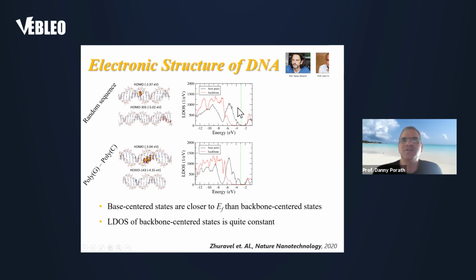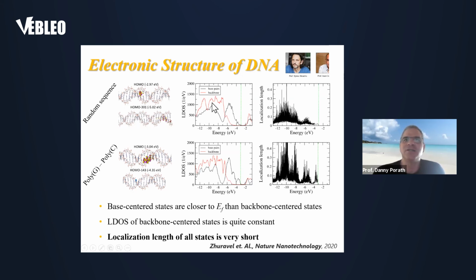So you can see that the bases are closer to the Fermi energy, but also then appear the backbone states, and they're smooth. So there are states for both the backbone and the bases. Now, when checking the localization length versus the energy, the localization length was very, very short. And that means it cannot be, as we thought when we looked at the experimental results, that there is some kind of band conduction.